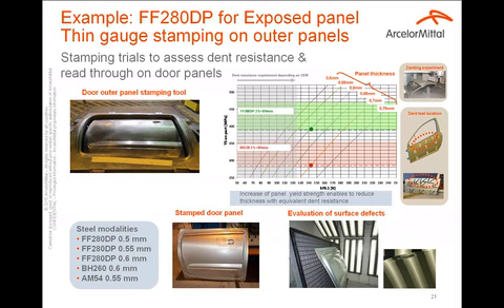Here we have chosen one example regarding our new grade for exposed panels called FF280DP, full finish 280DP. It's a dual phase grade for exposed panels. So we run stamping trials in our press shop on very thin gauge to assess dent resistance and red-through on door panels. On the graph, you can see the yield strength on the part achieved on the exposed outer panel as a function of the dent resistance requirements. You can see that FF280DP in 0.6 millimeter has the same dent resistance performance as BH220 in 0.7 millimeter. So the weight saving potential is huge.